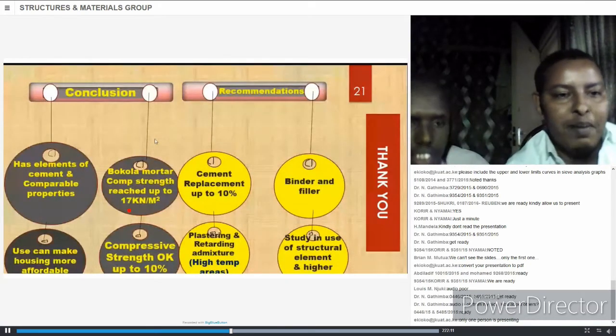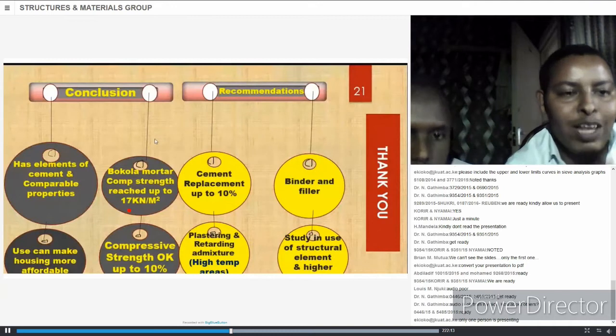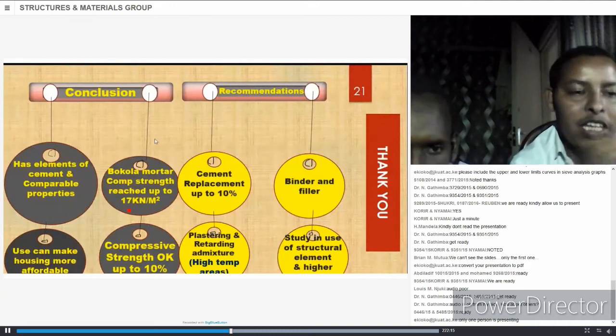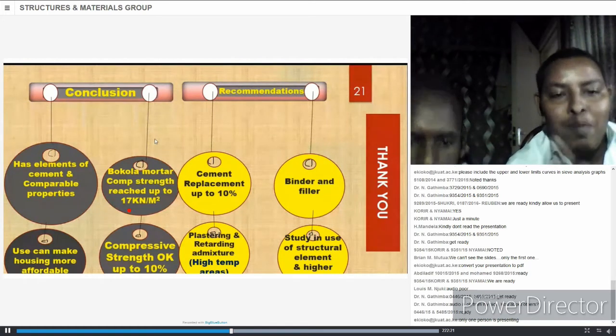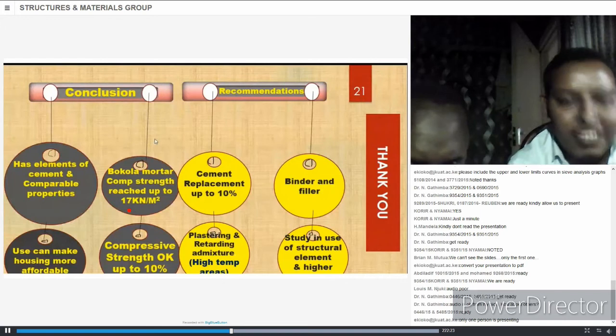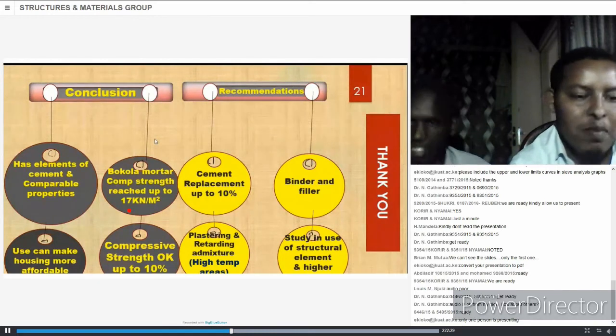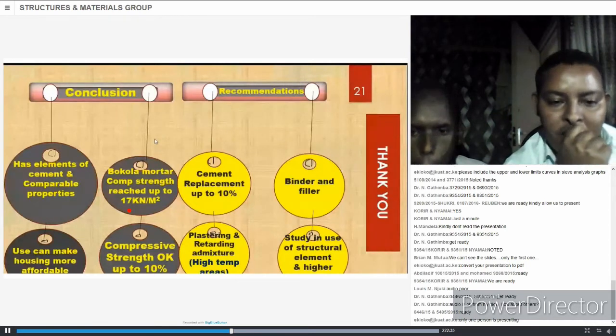On to conclusion and recommendation. Based on objective number 1, we realized that bokola soil contains elements of cement and could show comparable properties. This includes setting time and fineness, all of which we showed the values. Bokola mortar also had compressive strength reaching up to 17 kilonewton per square meter, which is generally good. The use of this material can make housing more affordable, especially in large projects. Compressive strength in which we use this material as a binder is okay up to and including 10%.